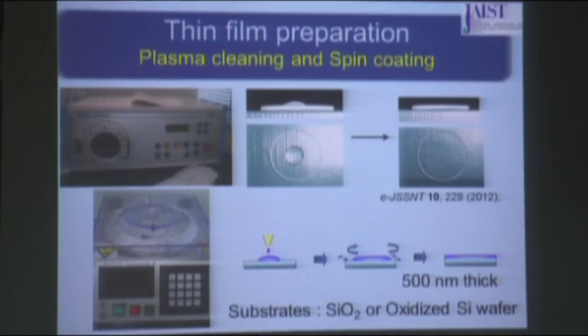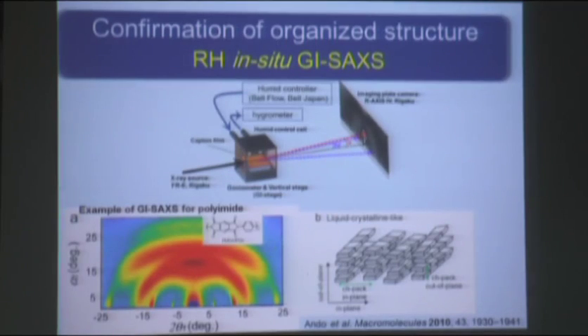To make it simple, a very easy technique: using plasma cleaning to make a hydrophilic surface on the substrate. The substrate is shown here. Like this. This is hydrophilic, this is water. And by spin coating we can fabricate a very good thin film. The thickness is around 500 nanometers. Okay, to confirm the organized structures, we can use RH in-situ, relative humidity in-situ, grazing incidence small angle X-ray scattering. This is an example of the polyimide case.